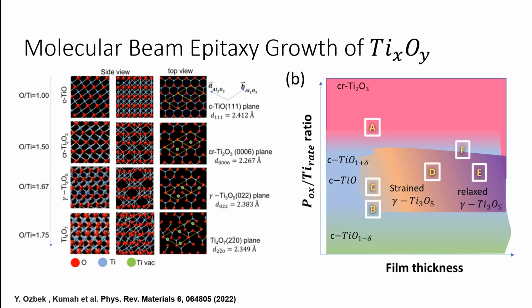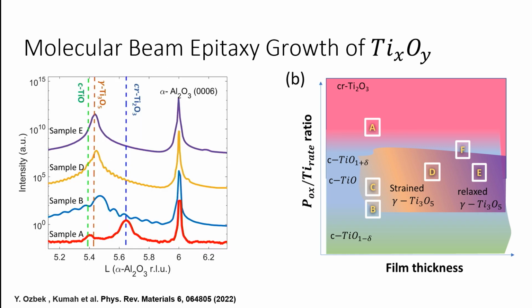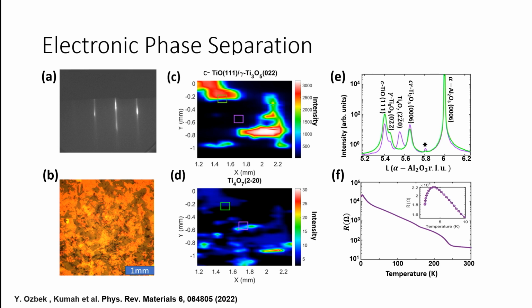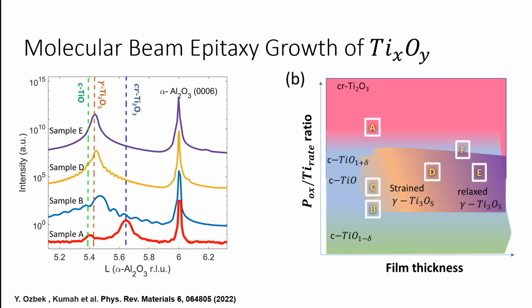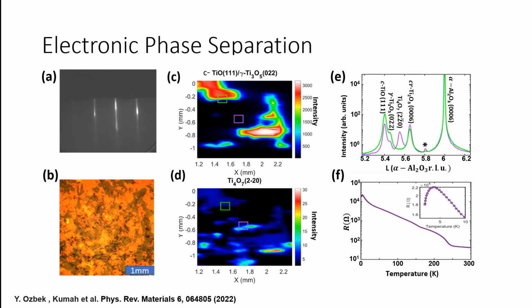And some of these phases here are superconducting, and Ti2O3 is not superconducting. And so we're able to grow these materials under different conditions, get the different phases, and get all these different properties. And under certain conditions, for example, if you're around this phase boundary here, we can actually get materials where we have spontaneous phase separation. So this is a light microscope image of a sample where you can see these dark and bright regions.